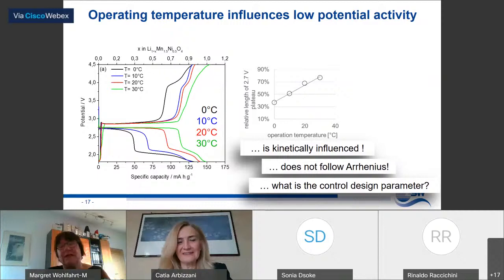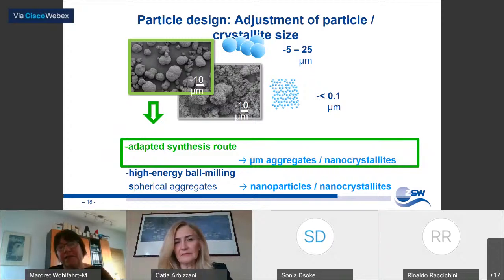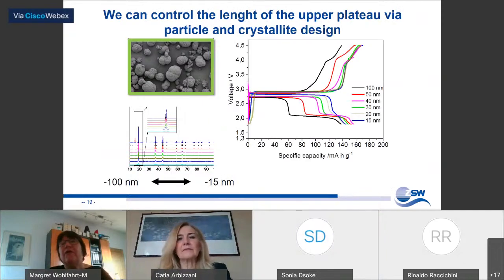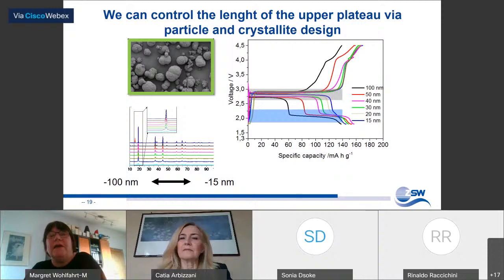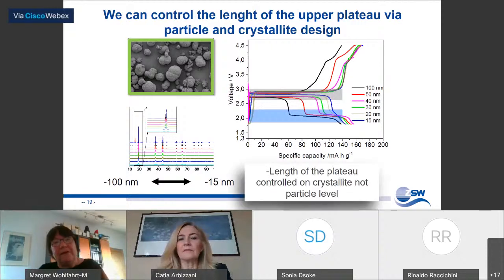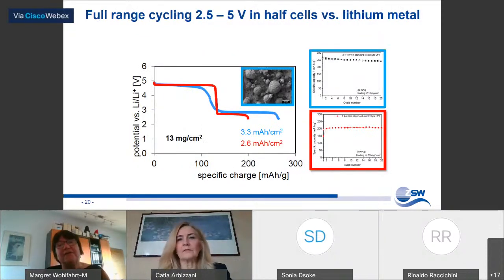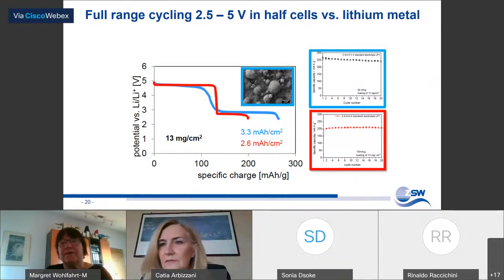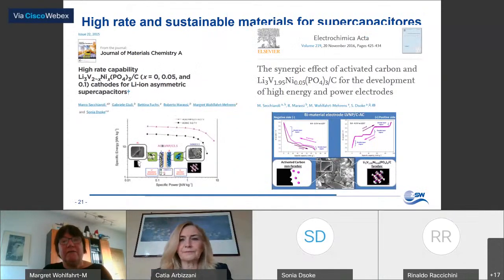So at the end, we found out that this plateau is kinetically influenced, and by proper adjustment of the particle and crystallite size, we were able to design a material which gives a quite high capacity of more than 200 milliampere hour per gram, and the length of the plateau is controlled by the crystallite and not the particle level. These are the results of half cells which work very well.